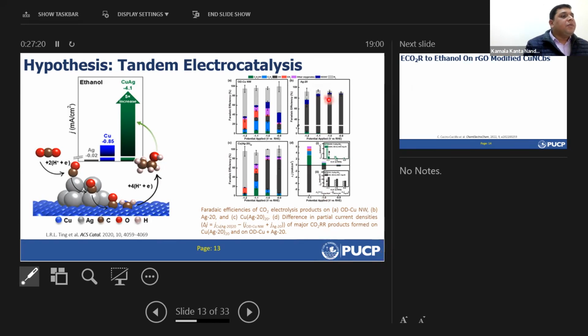Theoretically it looks correct, but practically, when you look at the Faraday efficiency of product formation, you end up either with a higher concentration of carbon monoxide, this black, or with a higher concentration of hydrogen. Although you are improving the ethanol formation over ethylene, we are not getting appreciable Faraday efficiency for ethanol formation. So we thought about why it is happening, because we know that gold, silver, platinum are very good catalysts. If they are coupled with another metal, whatever metal that is, they will not lose their properties, they will produce CO. So CO is produced more than the C-C coupling on the copper surface. Therefore, we are obtaining a higher amount of CO. And of course, hydrogen evolution is the competitive reaction to CO2 reduction, so we are obtaining a lot of hydrogen.